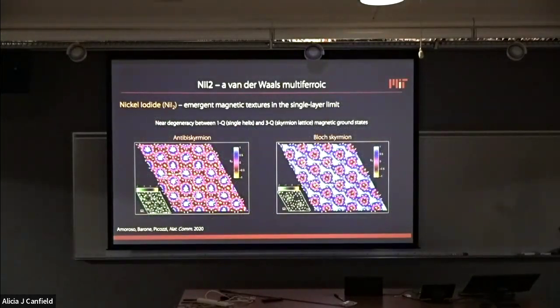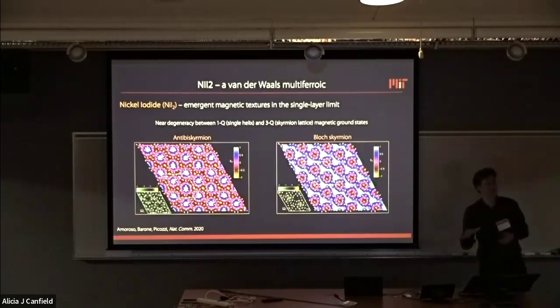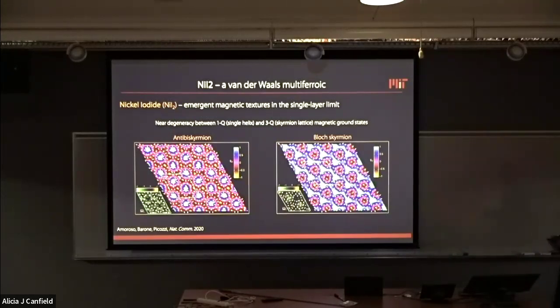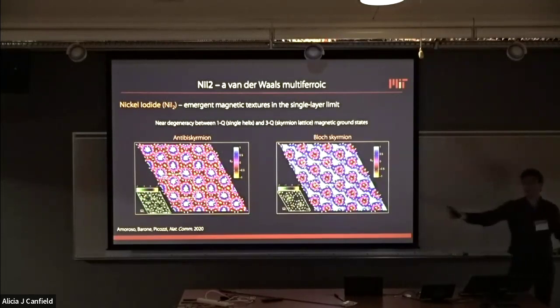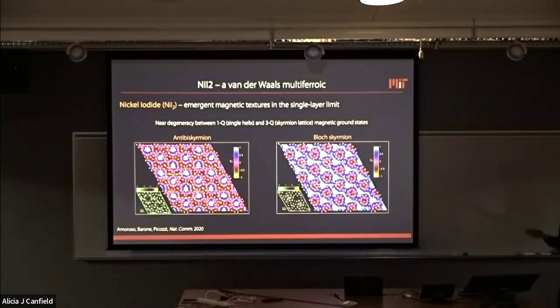Now, the reason that motivated the work that we did was the fact that it was proposed that this material in the single layer limit develops some topological spin textures, like skyrmions and merons, or even anti-merons. It's a spin helical state in the bulk, so it's a single-Q helix in the bulk. But in the ultra-thin limit, there was this proposal that the state would become 3Q. So you would have 3 helices superimposed on top of each other, and then depending on the relative phase, you could get some topological spin textures.